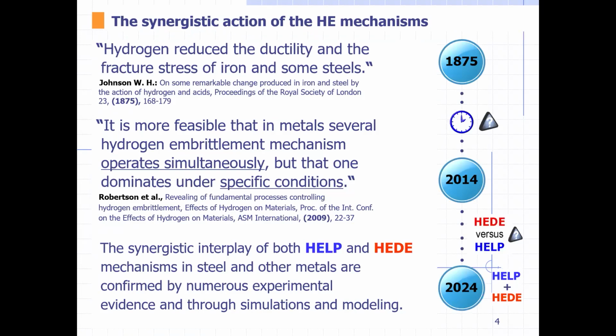Hydrogen is an old topic. In 1875, Dr. Johnson, in a famous paper, showed that hydrogen reduced the ductility. Then we have a 2014 paper by Professor Robertson from the US, which pointed out that several mechanisms of hydrogen embrittlement operate simultaneously. And then we proposed the HELP plus HEDE model as one of the options for synergy. So we can say nowadays that the synergistic interplay of various plasticity-mediated hydrogen embrittlement mechanisms, including HELP and the decohesion mechanism HEDE, is confirmed by numerous experimental evidence and through simulation and modeling.